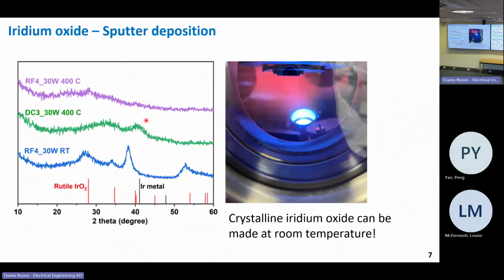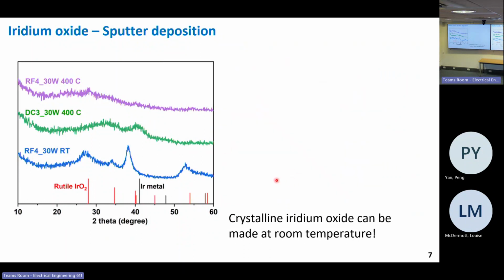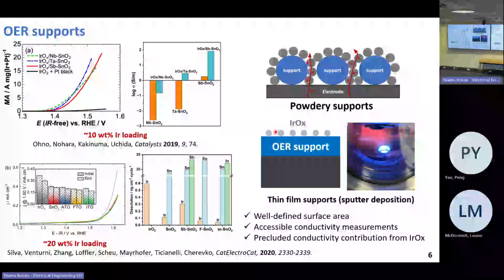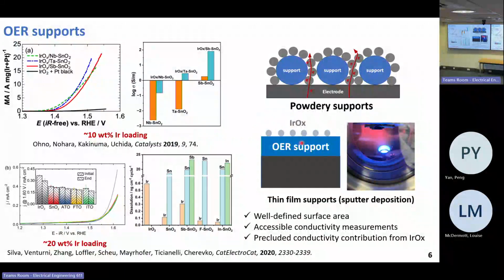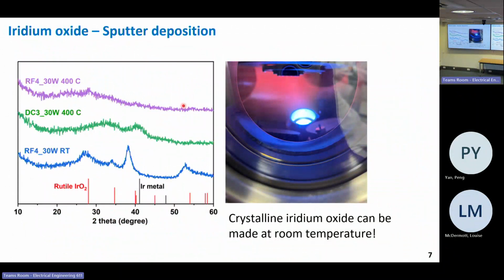So we've got a really expensive iridium oxide sputter target to sputter iridium on top of this support, so it has an even distribution on the support. After a few months of optimization, we can now get highly reproducible and crystalline iridium oxide at room temperature.